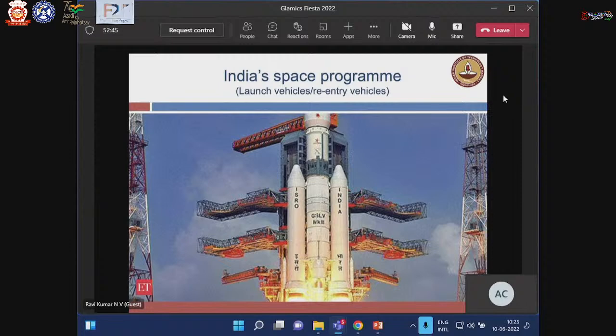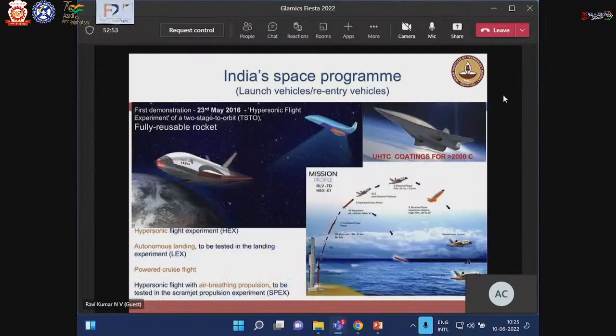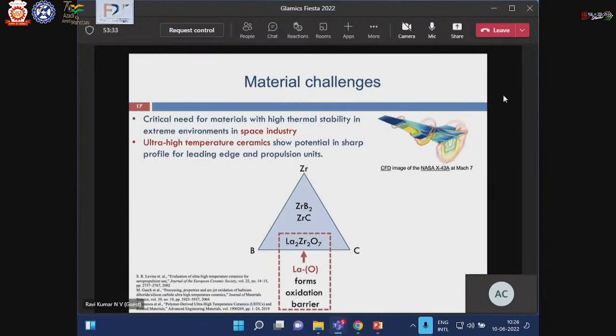In recent times, we have been working with the Vikram Sarabhai Space Center to provide ultra high temperature coatings for their re-entry vehicles. Here, we had to move from our comfort zone. We typically have been working on silicon-based materials for the last 20 years. However, due to a lot of practical limitations under very harsh conditions, silicon based materials are not very useful, and we were trying to work with ISRO to develop completely non-silicon based, non-oxide based materials, based on rare earths, that can be used as coatings safe till 2000 degrees and above. So we have been working on the zirconium boron carbon system and incorporating various rare earths such as lanthanum, gadolinium, dysprosium and so on.